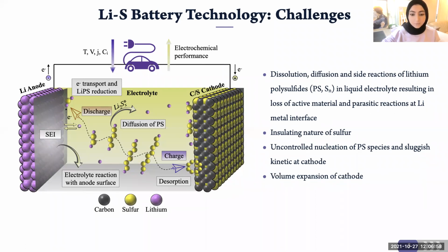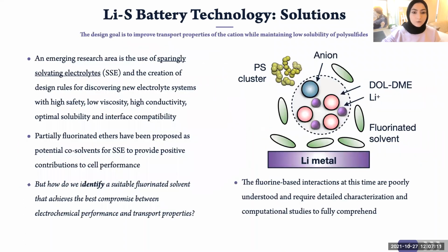So to have a successful application of lithium-sulfur batteries, we need to design optimal electrolytes and electrode-electrolyte interfaces to mitigate the lithium polysulfide shuttle process. And one of the possible solutions include the use of fluorinated ether solvents, which are shown in green here. The solvating power of these fluorinated solvents is largely weakened because of the high steric hindrance of the fluorine atom compared to the hydrogen atom in conventional glyme electrolytes or solvents like DOL and DME in lithium-sulfur battery. And the fluorinated solvents also participate in the formation of a stable solid electrolyte interface on the lithium metal anode. But the fluorine-based interactions in the electrolyte at this time are still poorly understood, and they require detailed characterization and computational studies in order to fully comprehend.